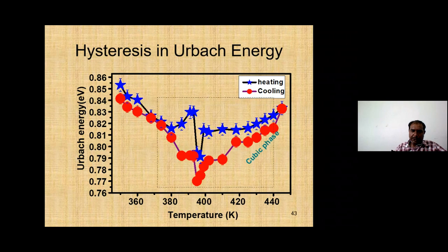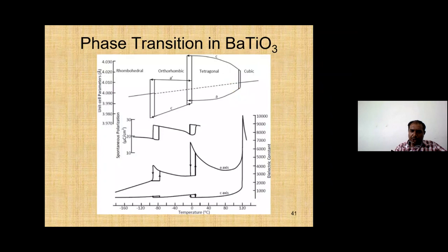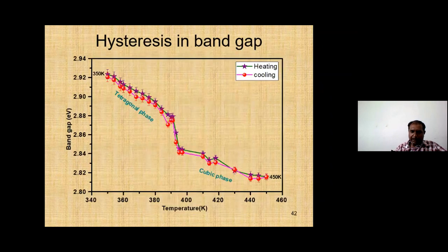In fact, we have repeated this experiment more than 10 times, and the result reproduces exactly every time, with some error bars obviously. So what does it mean? It means that if you are looking at the lattice parameter, the dielectric constant, or the band gap, then these are not really a proper order parameter to look at the region of hysteresis, or region of phase coexistence. If you are familiar with hysteresis, then you will realize that in the case of a first order phase transition, some amount of phase in the hysteresis region coexists, meaning the sample coexists in two different phases. In this particular case, it is present in cubic and tetragonal both.